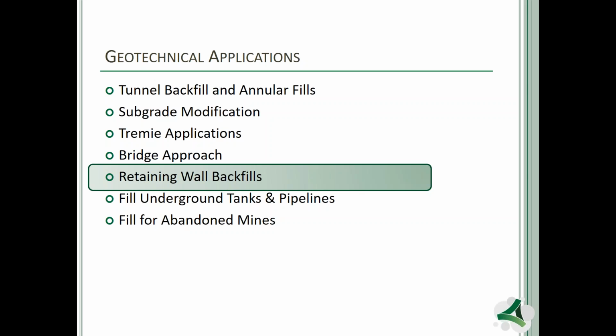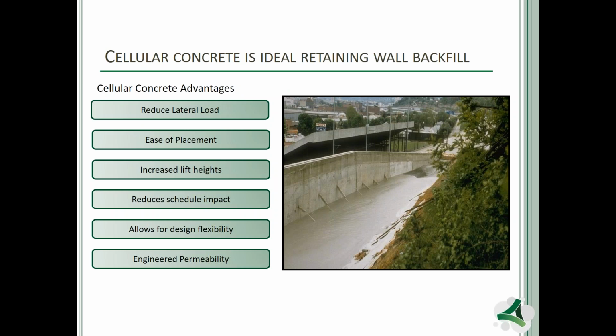When looking at various retaining structures with the utilization of cellular concrete, anytime you replace the sliding wedge of the soil and stay above the angle of repose to create a vertical fascia wall, once the cellular concrete is cured, that vertical fascia wall will end up having a zero lateral load factor. The only time you're going to have a lateral load will be during the liquid phase of the cellular concrete. But once it's cured, you will end up having a zero lateral load factor as long as you've replaced the sliding wedge of the soil.